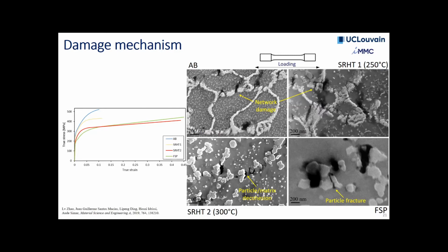And we're actually thinking now of wire arc additive manufacturing as well, which is also expectedly leading to larger microstructures. But what I think is very interesting is that quite a few years ago, Florent Anarle, who was also with us at some point and is now a postdoc, did his PhD looking at friction stir processing of 6061 alloys. And he actually showed that reducing the size of the intermetallic particles was also improving the ductility of these materials. So I think this is quite a general behavior. If you reduce the size of very large particles, you can actually delay damage.